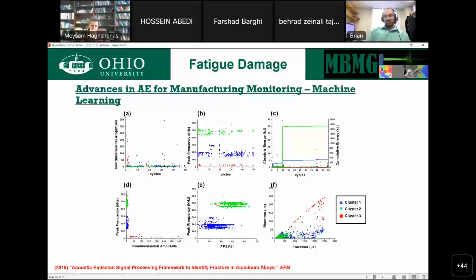And what we can see is, as we look through this, there tends to be a shift in cycles from certain mechanisms like the green, which is more dominant early on, to the blue, which is more dominant later on. And tying that back to the microstructure now, there is the potential to make an argument that the green may represent nucleation and the blue may represent growth. Without direct observation, that is a difficult argument to make, at least until you've done it a few times.